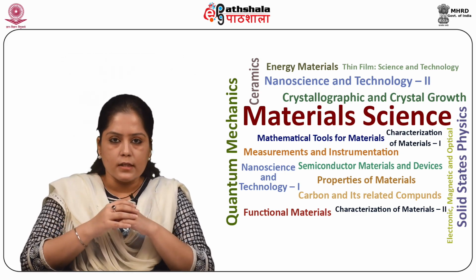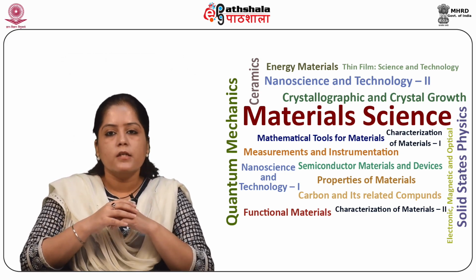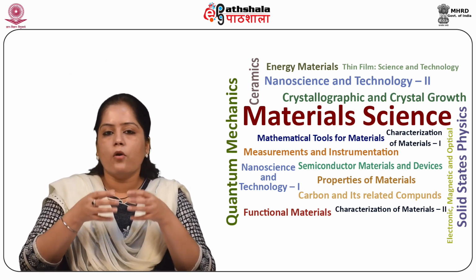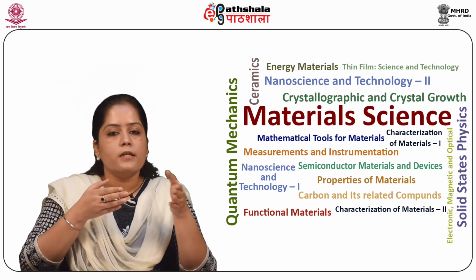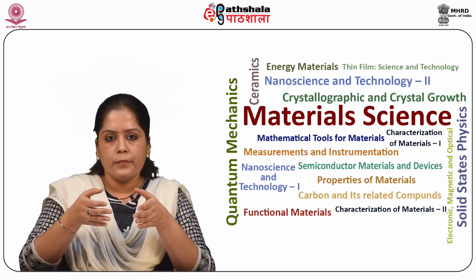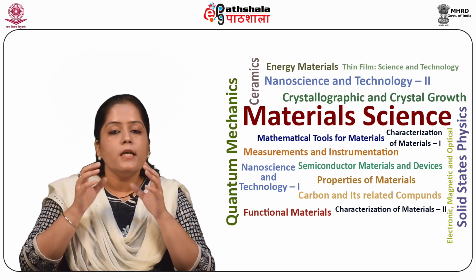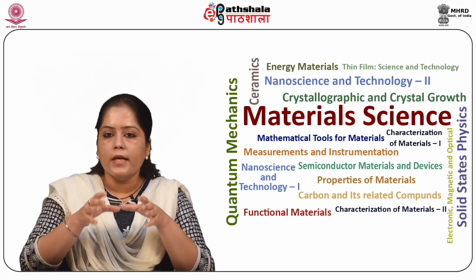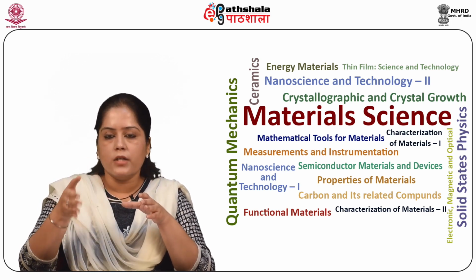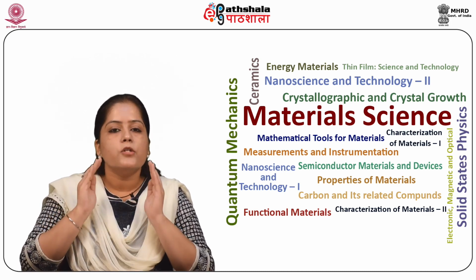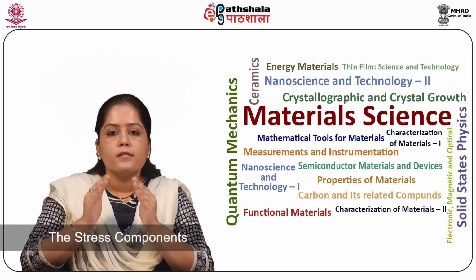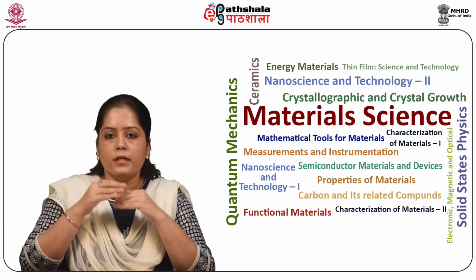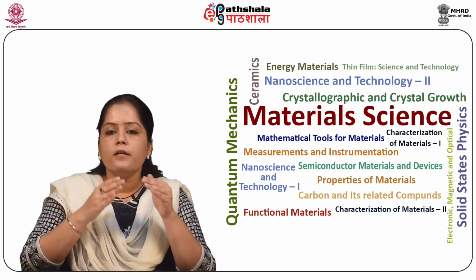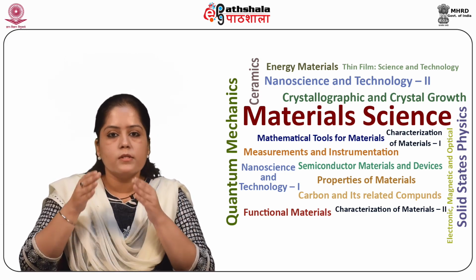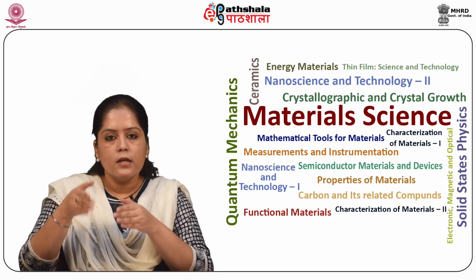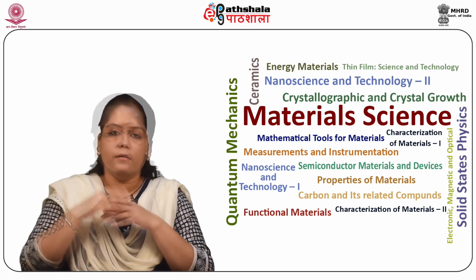So if a crystal is subjected to a general state of stress, that is sigma ij, then each of the strain components epsilon ij is related to each of the stress components by this relation: epsilon ij equal to Sijkl sigma kl.